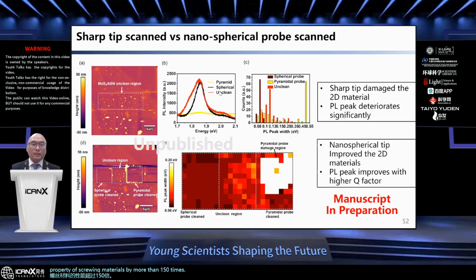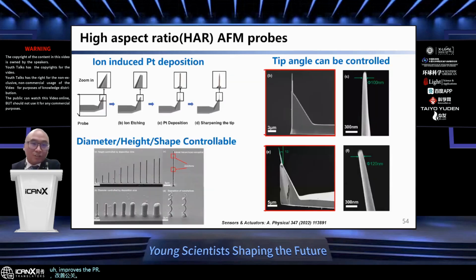And recently we did a comparison. We treated the surface with both the spherical probe and the sharp probe. You can see the sharp probe even broke the 2D materials. The PL peak was lost, but our spherical probes clearly removed the bubbles and improved the PL effect.